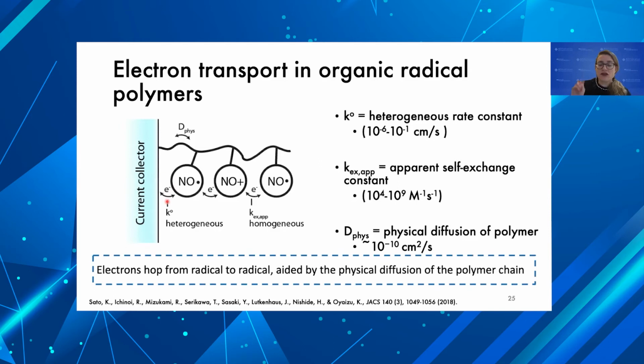So we think about this in terms of two rate constants. One rate constant is the homogeneous apparent self-exchange constant, and the other one is the heterogeneous constant, where it crosses the boundary into the current collector. What was found was that the segmental mobility of the polymer is really key in making this happen. So we need to think about the mobility of the polymer. If you can see my hands here, my hands represent the radical groups. As the polymer wiggles around and diffuses, the radical groups can go along with that, and sometimes they get close enough to each other that an electron can transfer. So that's really important.